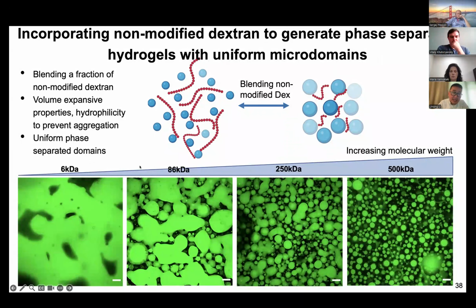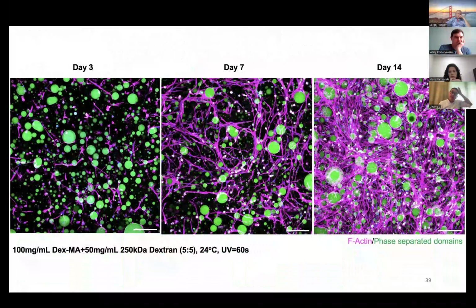You can see that as you increase the molecular weight, you are able to achieve relatively better controlled domains than before. So we're able to use this approach for cell studies. Here we show that as you increase the days, you have more of the interfaces. The cells can sense the matrix and use this interface to really grow. And then by day 14, you essentially have completely cellularized components.